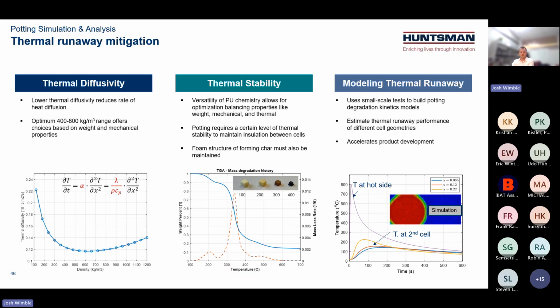I've witnessed two different systems, one UL94 HB system up against a UL94 V0 system at an OEM, in a battery pack, where the system that was rated for horizontal burn rather than the full V0 actually prevented flame escape for many minutes longer than the V0. And that's because the flame rating alone isn't a perfect indication. We found that diffusivity, that is finding the right density target and the right thermal conductivity of the material to prevent heat spread, is a pretty significant factor.